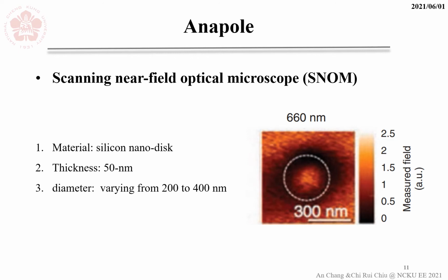Theoretical results were confirmed through scanning near-field optical microscopy experiments with 50 nanometer thick silicon nanodiscs of diameters varying from 200 to 400 nanometers.